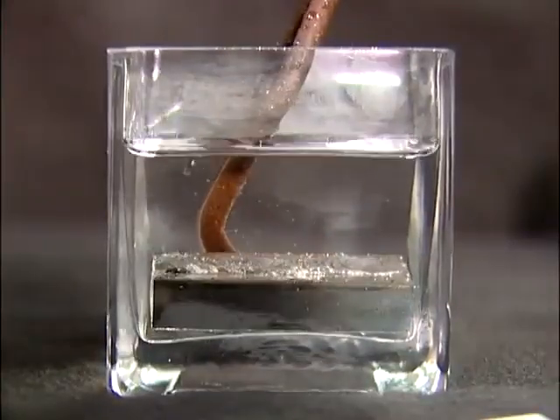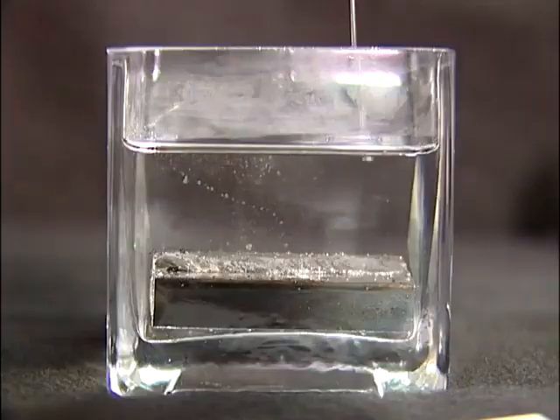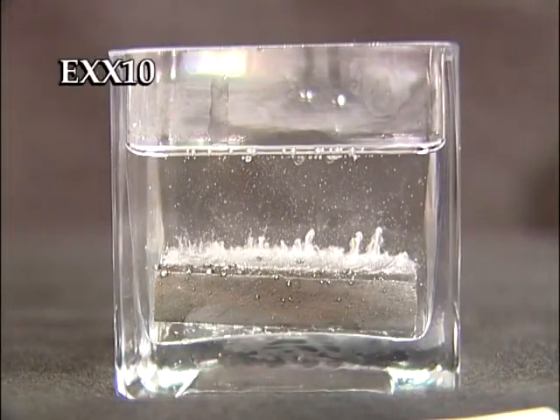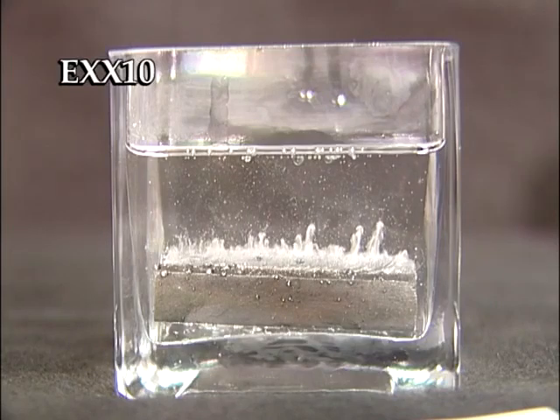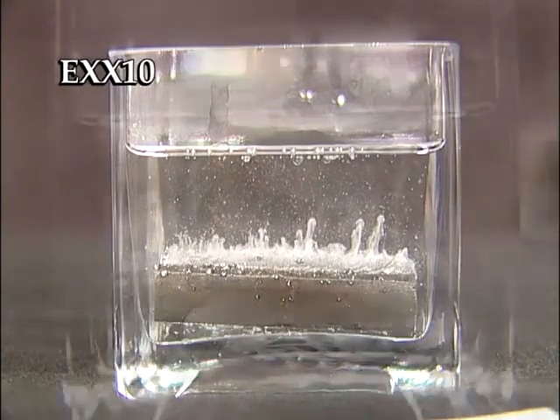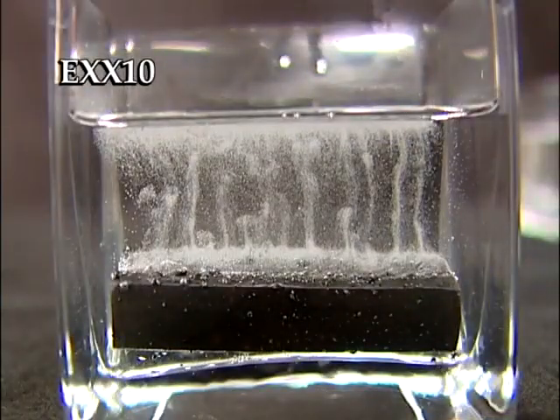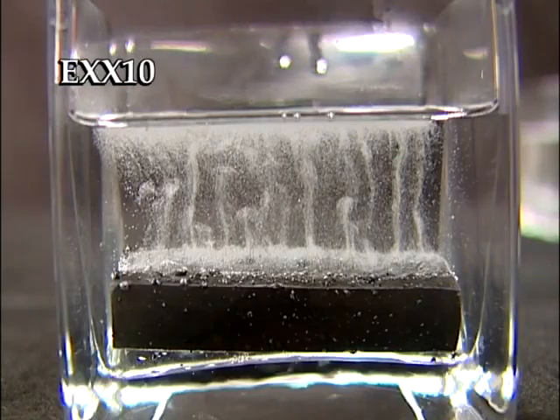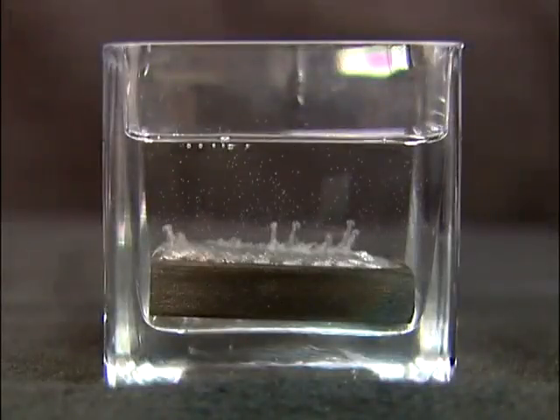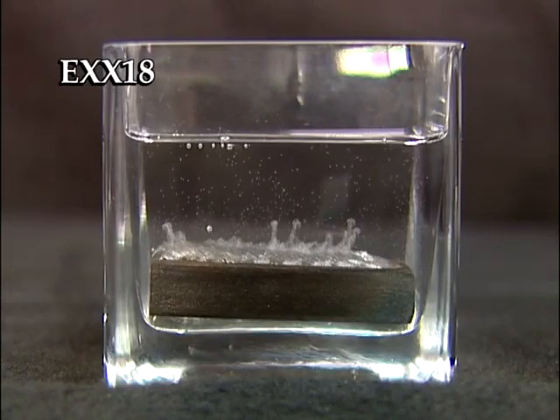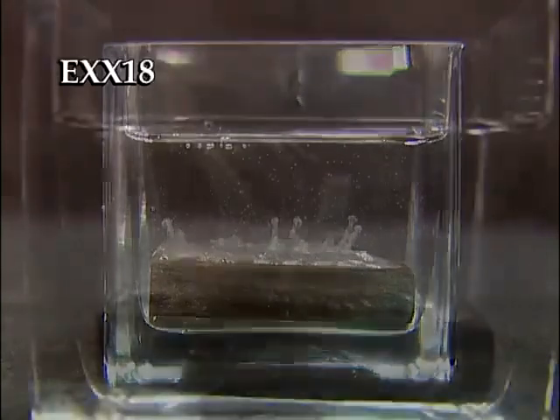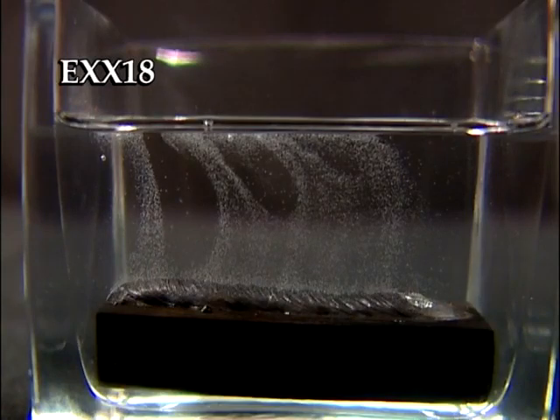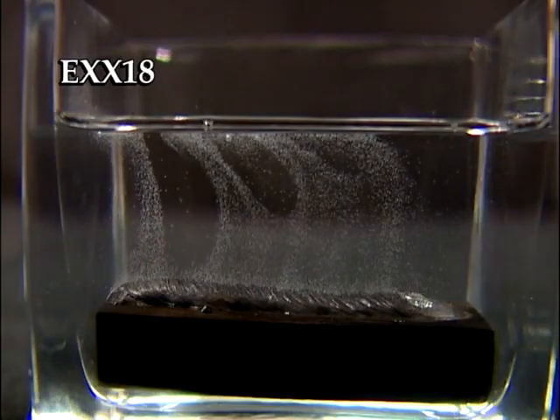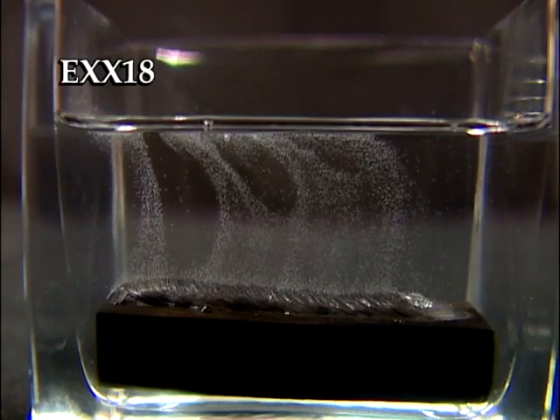Immediately after completion, the welds are placed into mineral oil, so the diffusion of hydrogen from the completed welds can be seen. The first sample was welded with a cellulosic-coated, high-hydrogen electrode and placed into room temperature mineral oil. A large number of hydrogen bubbles can be seen slowly diffusing from the weld. The second sample was welded with a low hydrogen electrode. Compared to the first sample, much less hydrogen diffusion is evident. This coincides with the fact that approximately 10 times less hydrogen will be introduced to a weld made with low hydrogen electrodes, compared to traditional cellulosic-coated electrodes.